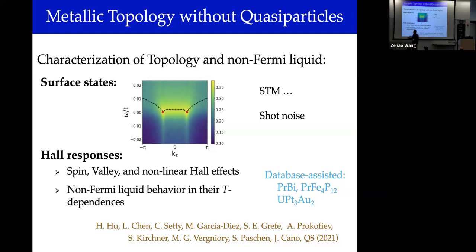And we can see that while the existence of these is consistent with the usual Berry curvature induced effects, the temperature dependence is highly unusual. So the temperature dependence here captures non-Fermi liquid. So in a way, these quantities would not have been non-zero if there were no topology associated with it. But here, there's a very good marriage of non-Fermi liquid aspect and topological aspects. And so we are continuing to pursue this direction.